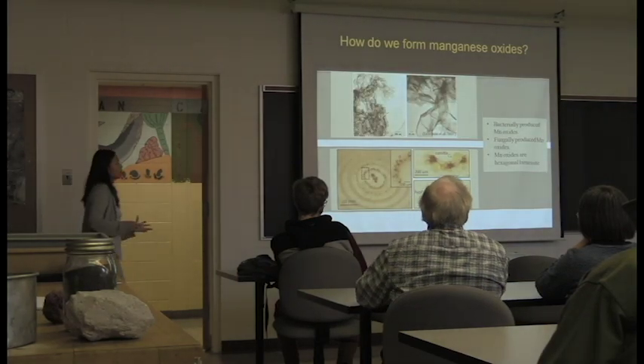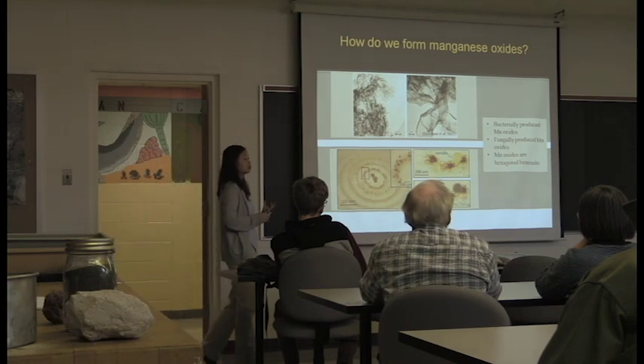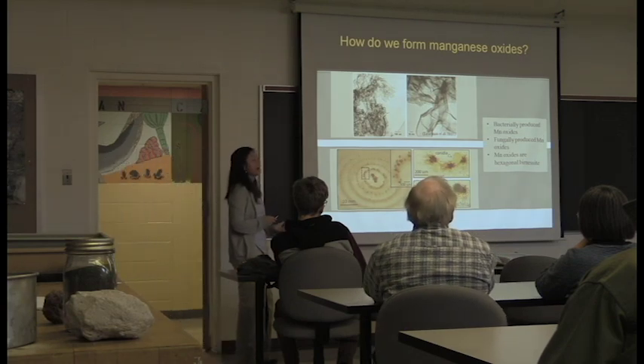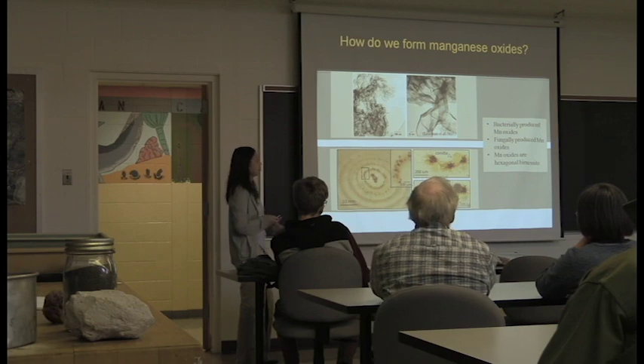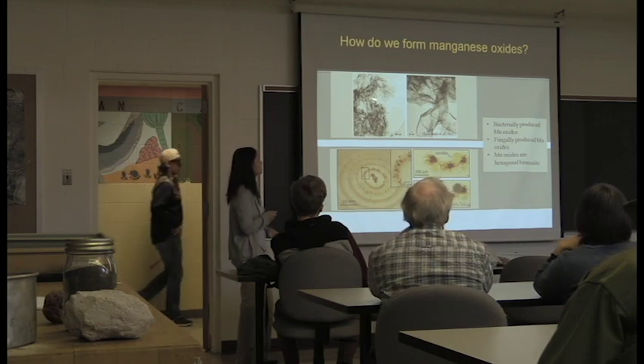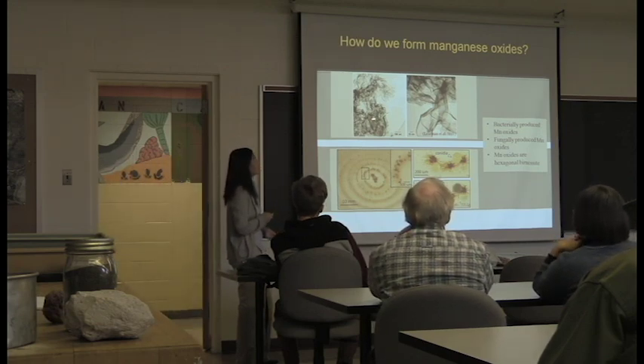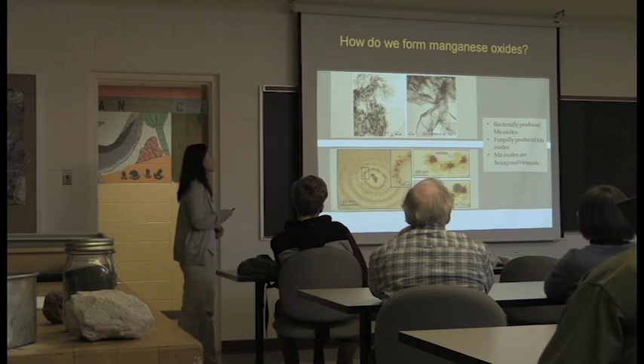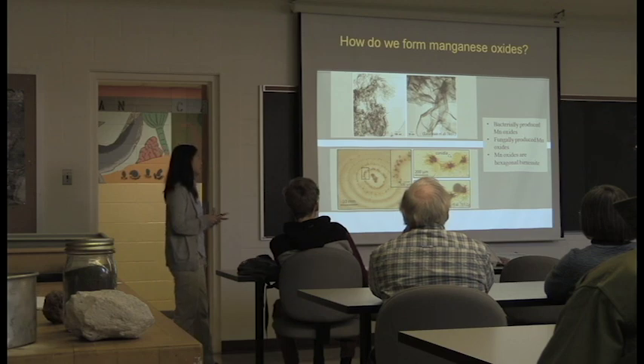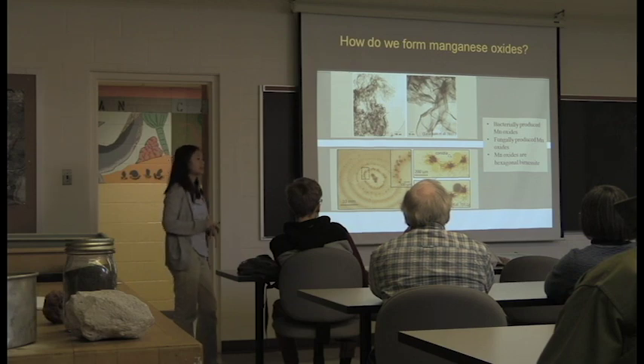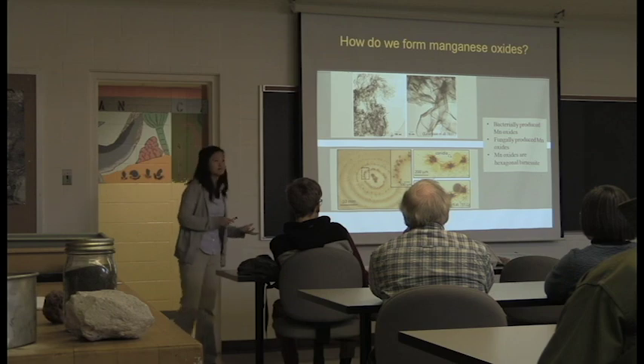And studies show that when you culture certain bacteria or fungi collected from the field, they can produce manganese oxide. So this is a culture where these black, wavy formations are manganese oxides precipitated by bacteria. And down here are some fungi that have been cultured, and these are the hyphae of the fungi. The reason they're dark brown is because they're coated in this manganese oxide.